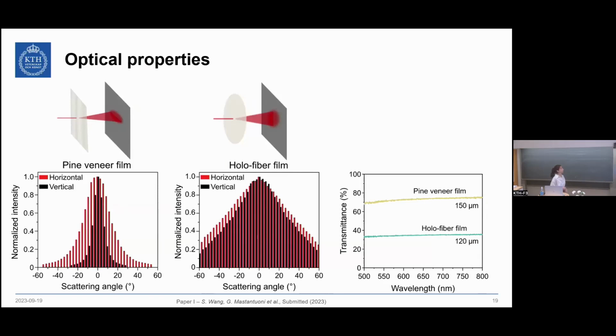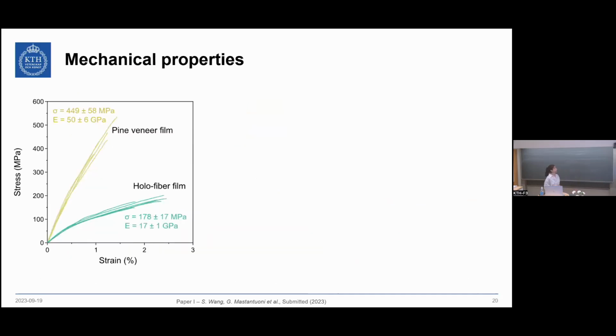Regarding the transmittance, we could also see that the aligned veneer, even if it's slightly thicker, still shows much higher transmittance compared to the hollow fiber film. The reason for this is that it had a lot fewer gaps inside the structure, so the scattering within the material could be minimized. Regarding the mechanical properties, we could see a similar behavior: the aligned material showed much higher tensile strength as well as Young's modulus compared to the random in-plane film.